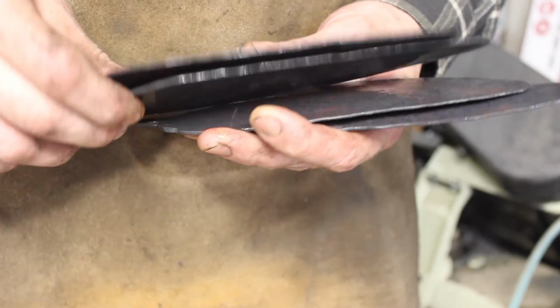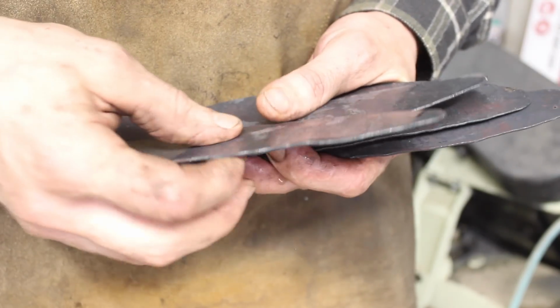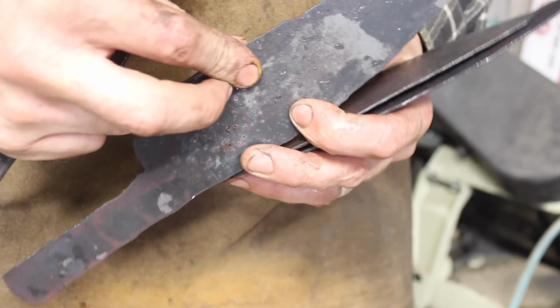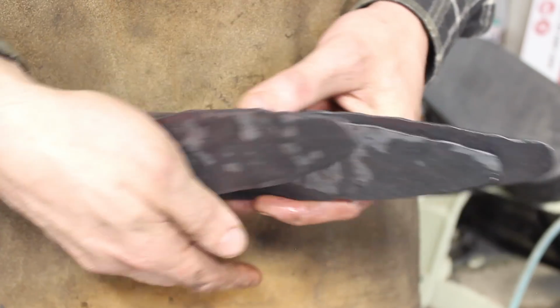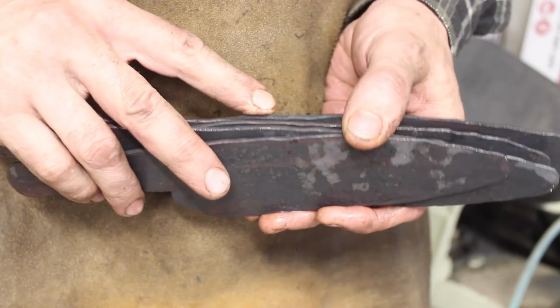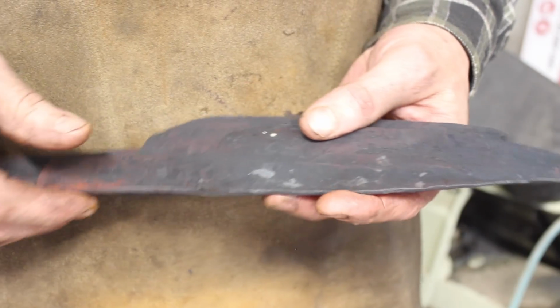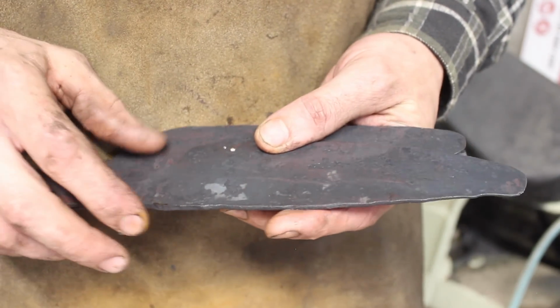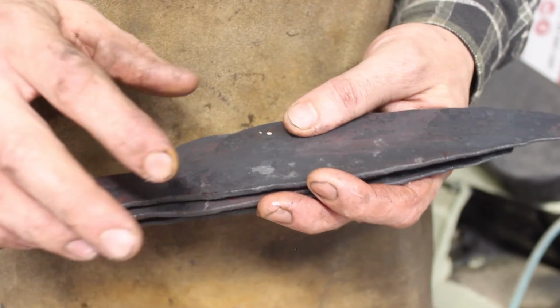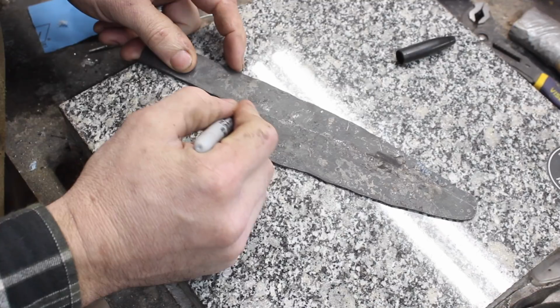Here's our blades, and as you can see, the bevel is forged in for the most part. They're about 1/8 of an inch thick here at the spine with a distal taper down. So this is an appropriate thickness for this type of knife. The next thing I want to do is go ahead and develop the profile on each of these for the next step.